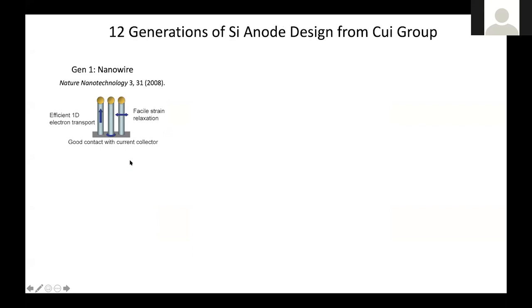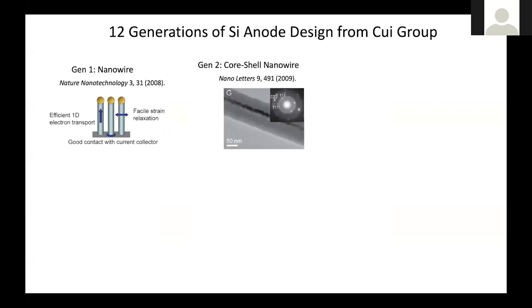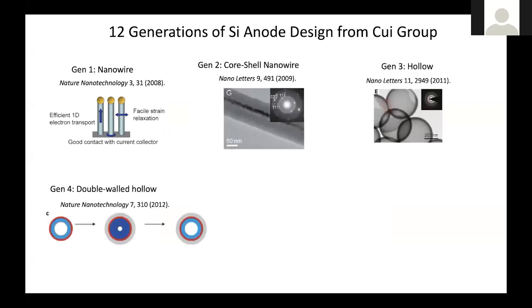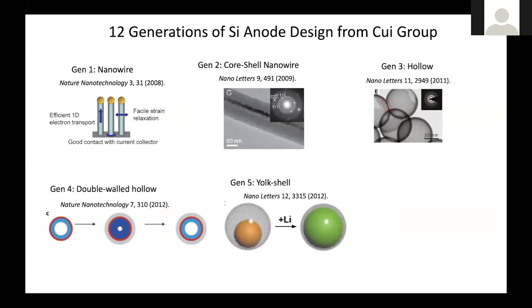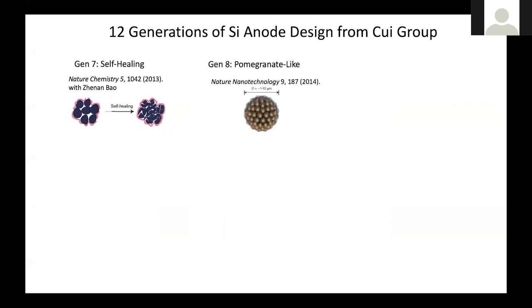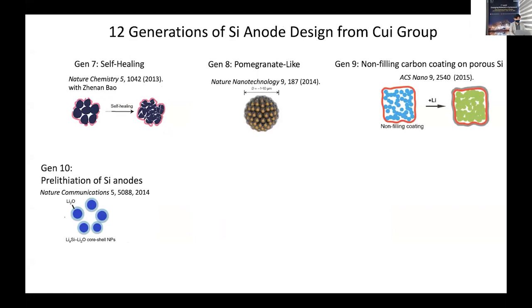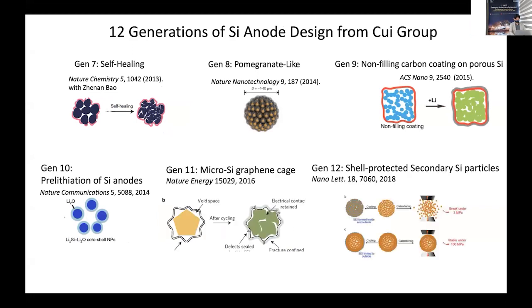Over the years, we have been through the design of nanowires, core-shell structures, hollow, double-wall hollow, yolk-shell, silicon hydrogel, self-healing, and pomegranate-type structures, trying to reduce the surface area of silicon nanoparticles by forming these secondary particles. And this has been 12 generations by now. This is really guided by the problem, as well as the tools we use to understand the problems that happen in the silicon anode.